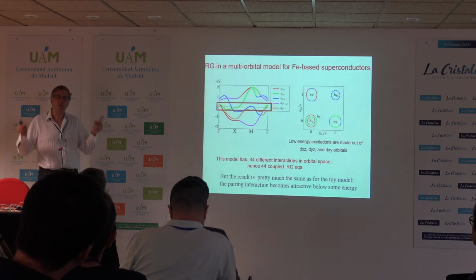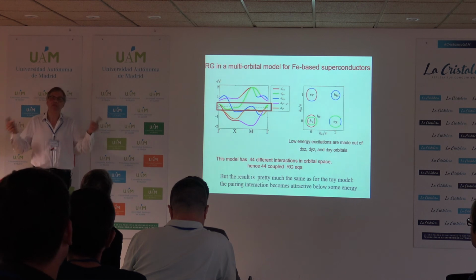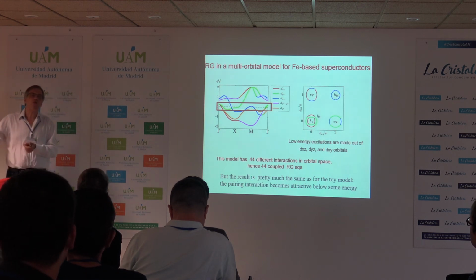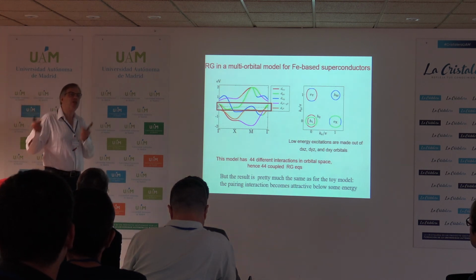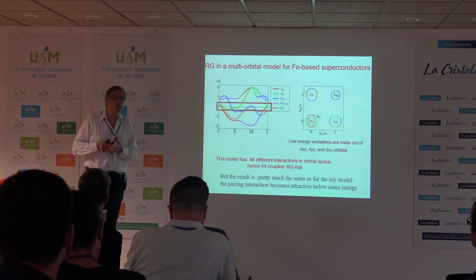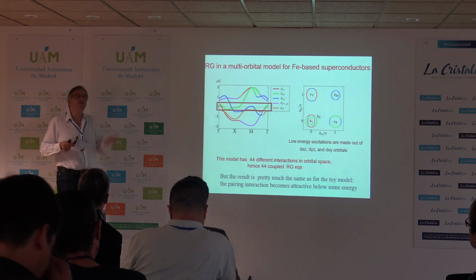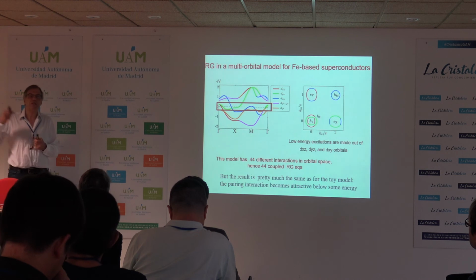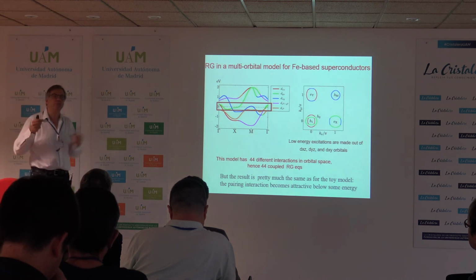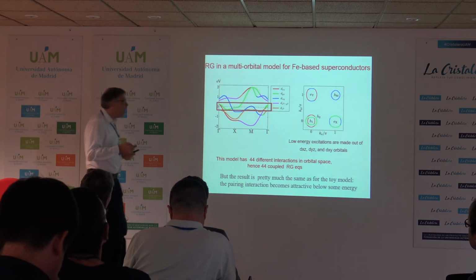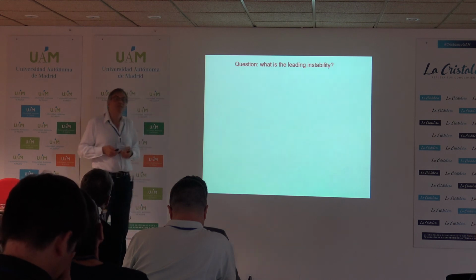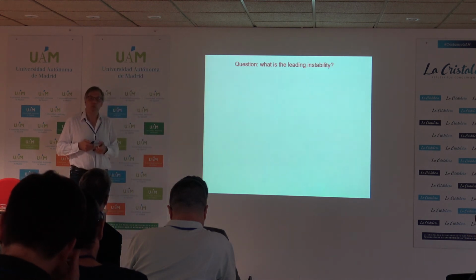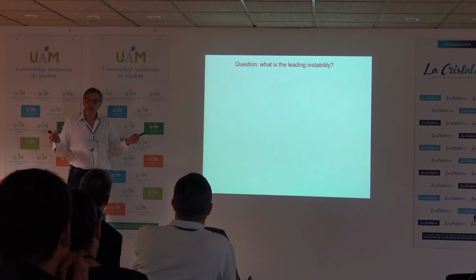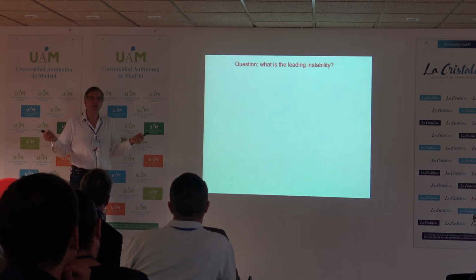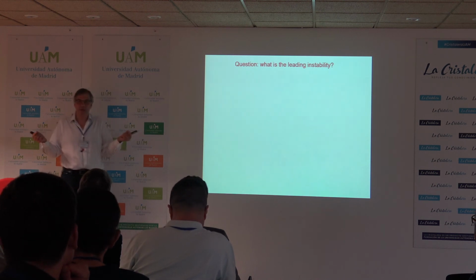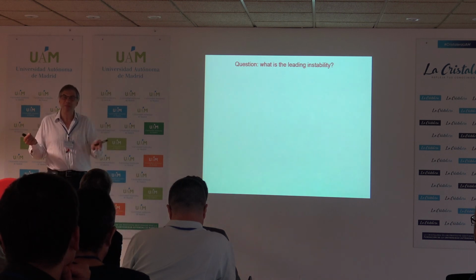There are two channels. One is the superconducting channel, s plus minus channel. Another is the orbital channel. Both are initially repulsive. And as the system tends to develop spin density wave, it basically changes the sign of interaction in both channels for the same reasons. Then you may ask the question, what is the leading instability of the system? What happens? By the way, the question can be put this way. Why not spin density wave? Why are we talking about superconductivity? The system tends to develop spin density wave.